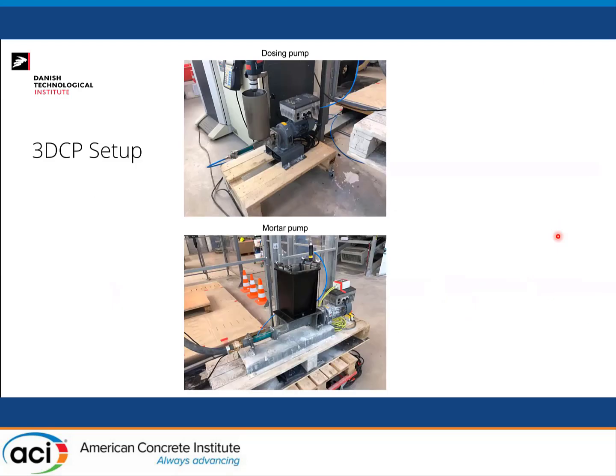Now, coming to how we put all the science together into a not so fancy, but effective and very compact mixing process. In the setup we have two pumping systems, one handling the mortar fraction, and one handling the CAC slurry. And the CAC slurry, as you see in the photo at the top, is always being agitated because it tends to segregate a bit. So if any of you attending this presentation is thinking about replicating such a system, that's just a hint: they should be agitated, because some segregation could lead to a problem.